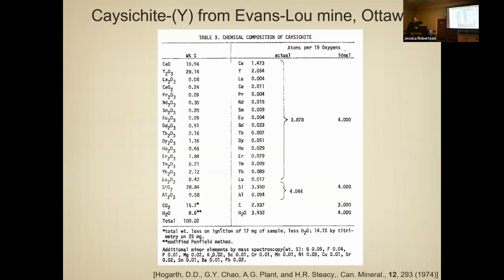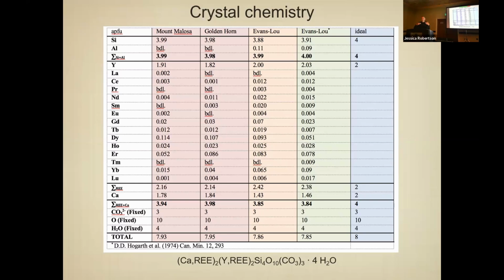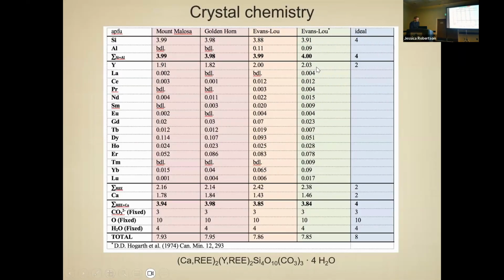Now, yet, comparing this with the type analysis, we are seeing that on the type material, there's a much lower calcium content. And so what this tells us, if we now do the full crystal chemical analysis in the microprobe, comparing all the different localities, so we have Mount Malosa, Golden Horn, the reanalysis of the Evan-Lu, and then comparison to the literature, we actually have phenomenal agreement between the type analysis from the 70s and the new analysis.